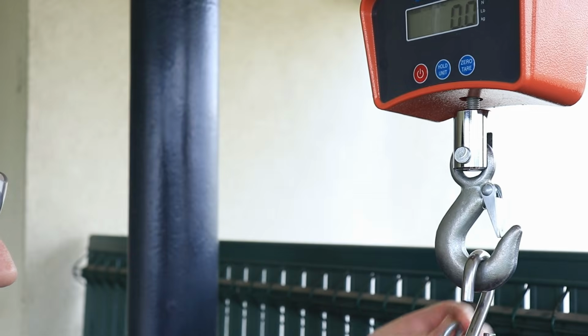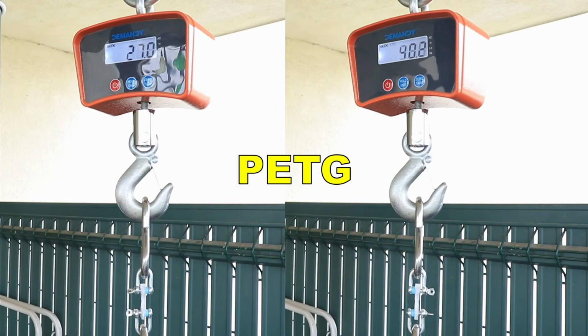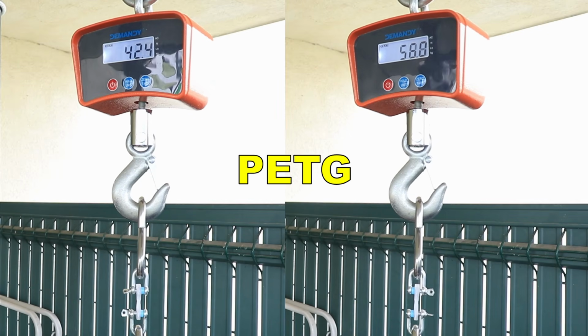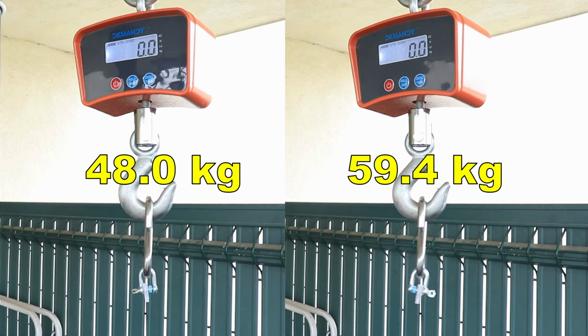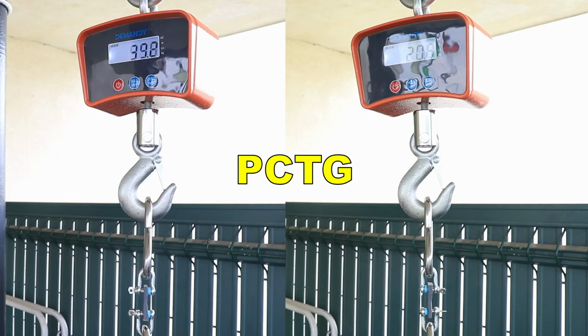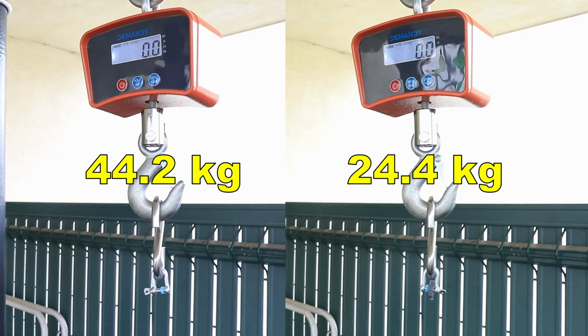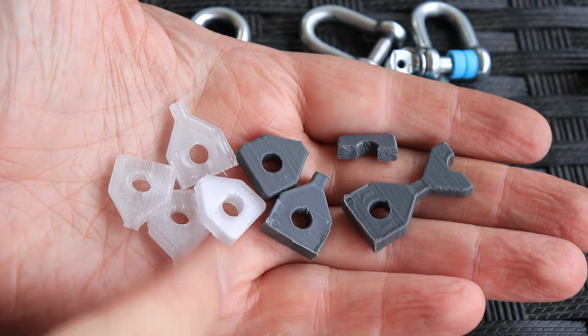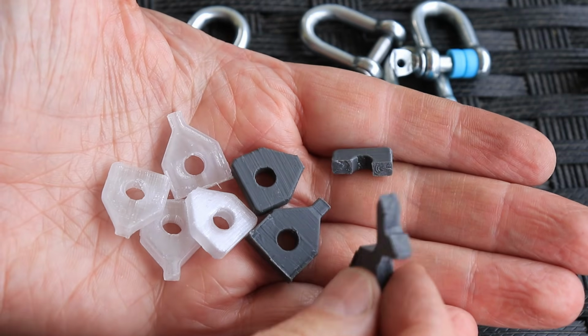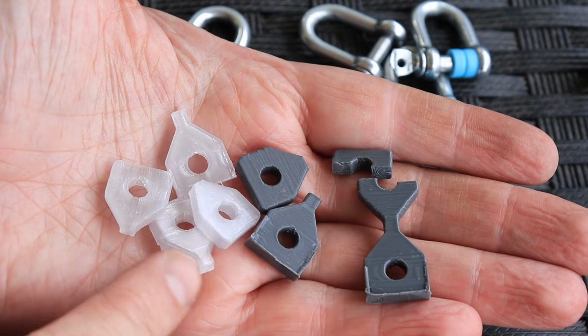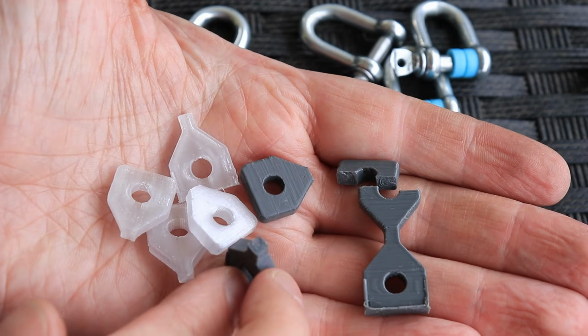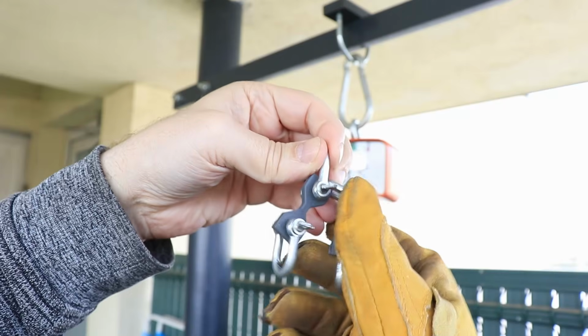Next is the layer adhesion test. So these test objects are printed in vertical position. And I'm starting with PETG. And then with PCTG, I noticed quite a difference in the two measurements. And one of the test objects didn't break on the smaller cross-section area, but next to the hole. So I decided to reprint and repeat the test with PCTG.